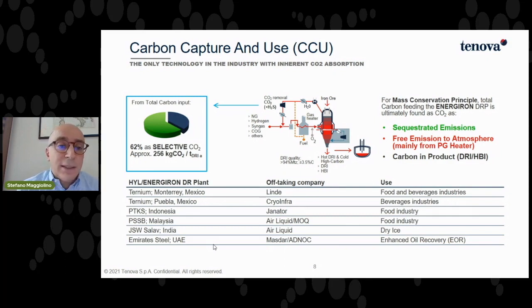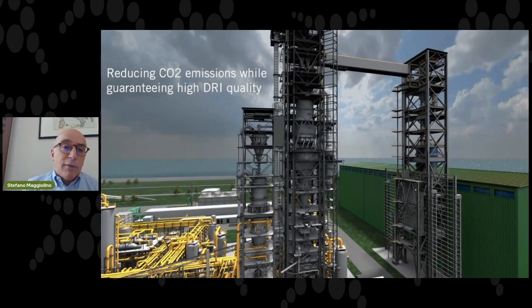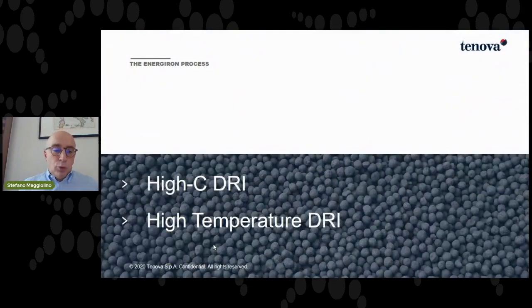If you calculate 250 kilos of CO2 per ton of DRI, Emirates Steel has an installed capacity of 4 million tons per year of DRI, and we can assume a value of 30 euros per ton of CO2, we're talking of tens of millions of dollars of revenues from the sale of CO2. And again, we are very proud that we can reduce CO2 in this way while guaranteeing high quality DRI. We now move to our capability to produce high carbon DRI and high temperature DRI.